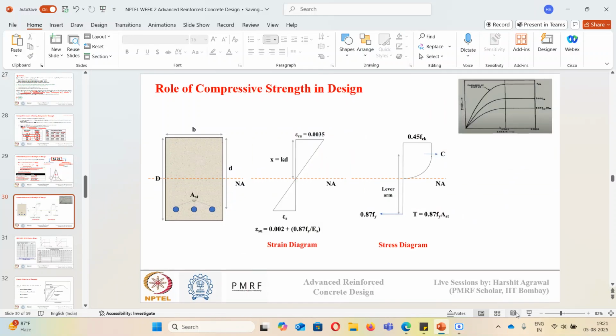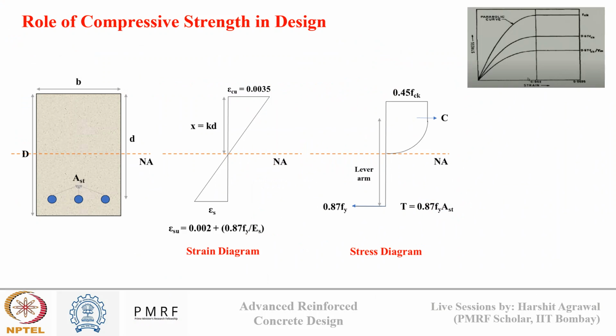If you see the idealized stress strain block for reinforced concrete that I have shown at the back, the stress in the extreme compression fiber is taken as 0.45 fck, and this corresponds to a maximum strain of 0.0035. So this is the role of compressive strength in the design.